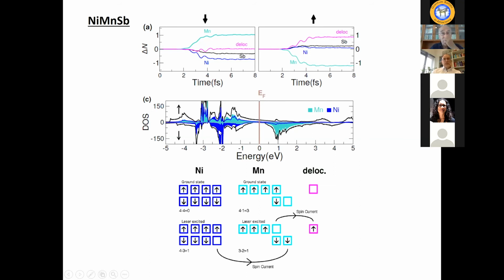And it's important to realize that at this kind of intensity that we have, the laser does not flip the spin, right? The magnetic component is small. So you have to go from a downspin orbital to another downspin orbital. And the only available downspin orbitals are on manganese.